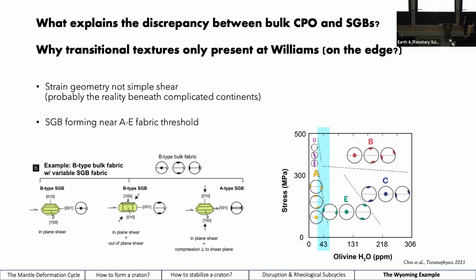So I won't belabor this too much, but the idea is that why we didn't see things match up like we see nicely in other peridotite locations can probably be explained because we're really the first ones to do this really detailed subgrain analysis, and it just shows that these continental regions are just not in simple shear. There's a much more complicated strain geometry that has no experimental counterpart to compare to. And also, we may be at a threshold where the water content may be flipping between different slip systems.